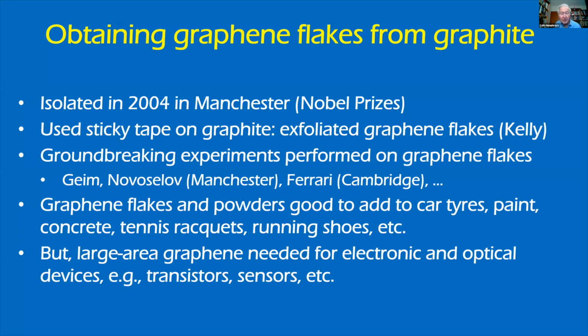And this was done in 2004 by Geim and Novoselov. They isolated graphene from graphite by using sticky tape on both sides of a lump of graphite, and then they pulled the sticky tape apart and got two blocks of graphene from the original first block, put some more sticky tape on, and kept pulling it apart until they got down to a single layer of graphene. And then they performed really difficult experiments on graphene.